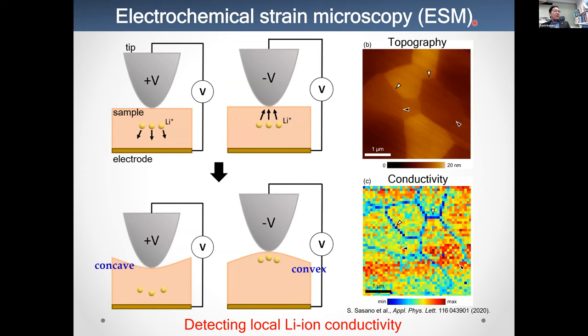This is the so-called ESM, and it is similar to AFM. When you apply a positive voltage, lithium ions diffuse from the surface to the inside. If you apply a negative voltage, lithium ions diffuse from inside to the surface. In this case, a concave surface appears, and in this case, a convex surface appears. Therefore, we can detect the local lithium ion conductivity. This is a very interesting method.